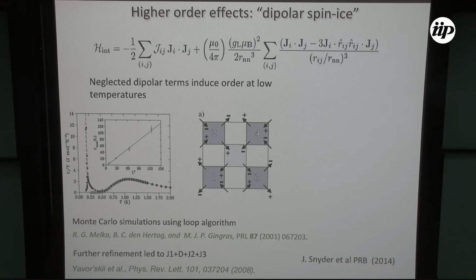The black curve here is the simulation compared with one experiment by Ramirez. You get this smooth Schottky type anomaly, but then you should get a very sharp transition into an ordered state. So this is a prediction of how that order would look. Essentially, it's still a neutral charge state, but of all the possibilities you have, you're restricted to 6. Essentially, what happens is that you get this change in order. So you see all these spins pointing in that direction, so you get like an antiferromagnetic ordering of these chains.